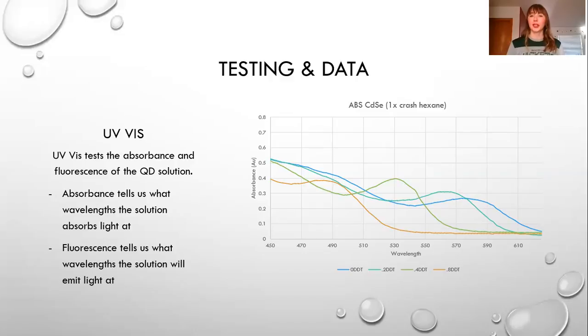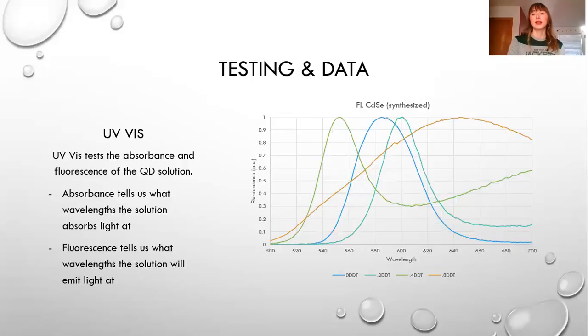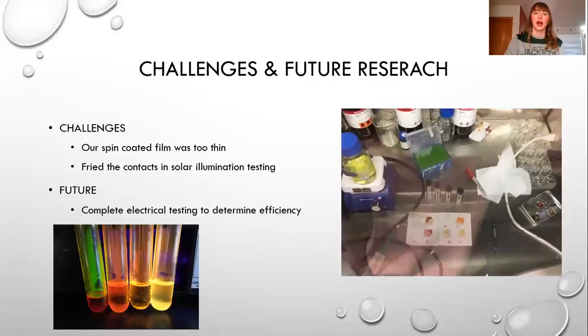So in this first graph up here, you can again see the 4 peaks. I didn't label these ones, but you can again see 0 DDT, 0.2, 0.4, and 0.8 as we talked about previously. So this shows that our quantum dots and various levels of DDT do in fact impact the properties of these quantum dots. Next up is fluorescence. This graph is a little wonky because 0.4 is over here, but you can still see the shift from 0.2 and 0.8.